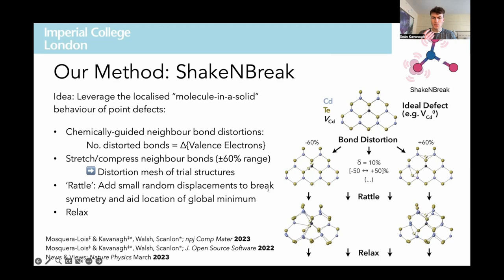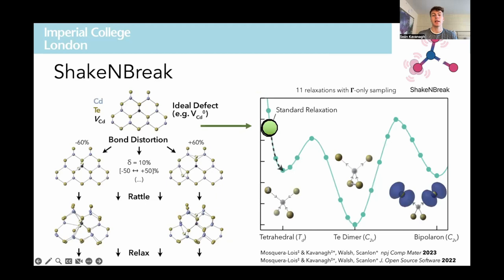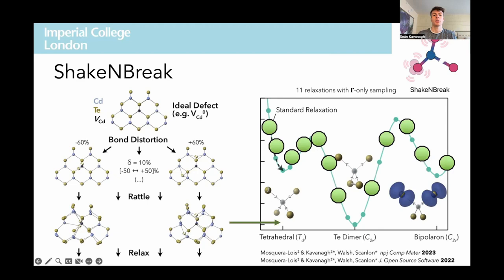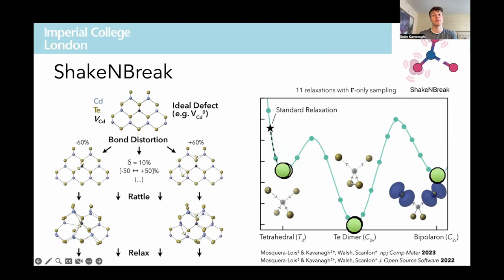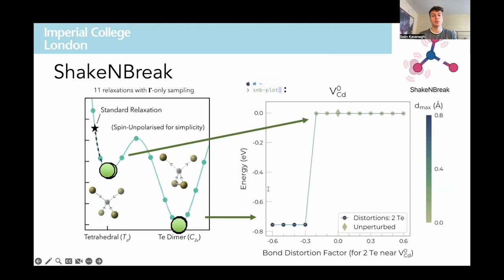We tested this choice across a range of cases with data provided in the SI of our paper. With this mesh of trial distorted structures, we then rattle them — meaning we add small random displacements to atom positions, which break symmetry and help disrupt the long-range lattice potential — which can aid in locating the global minimum. We then allow these structures to relax at a reliable level of theory using cheap, coarse numerical parameters, allowing calculations to run fast while retaining sufficient qualitative accuracy to identify distinct defect structures.